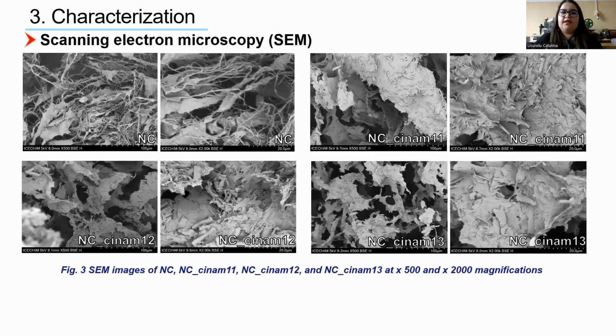The scanning electron microscopy images show that the microfluidization was not very effective in determining the dense defibrillation of nanocellulose. We can see fibers with nano diameter, but we can also see agglomeration of fibers. After the impregnation of the nanocellulose fibers with cinnamaldehyde, the individualized fibers become more difficult to visualize, and they appear more entangled and agglomerated, maybe due to their coating by cinnamaldehyde. Also, we can observe an increase in the pore size of the sponges with an increase in the amount of cinnamaldehyde in the sponges.